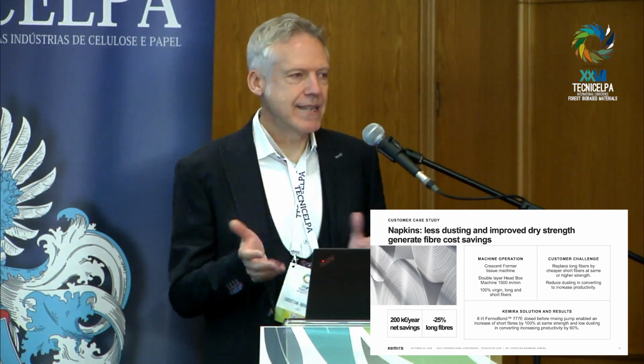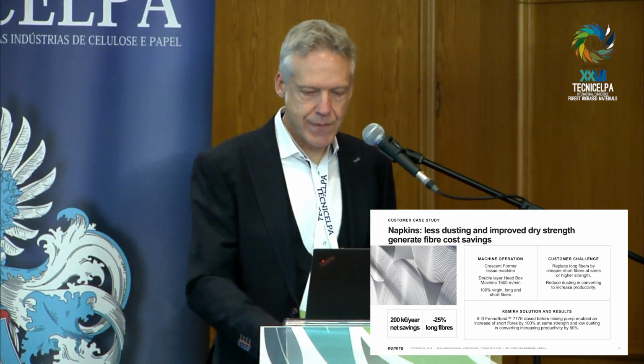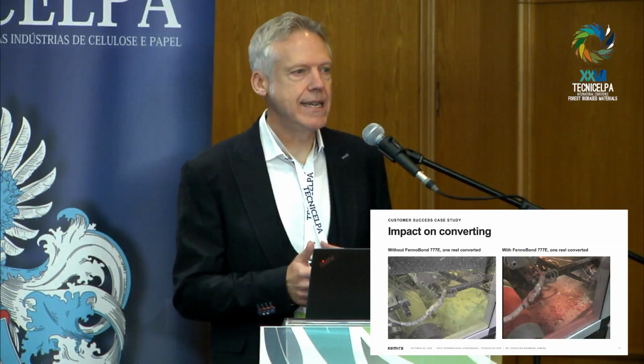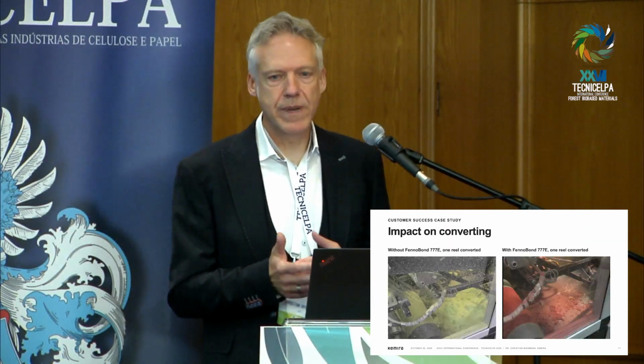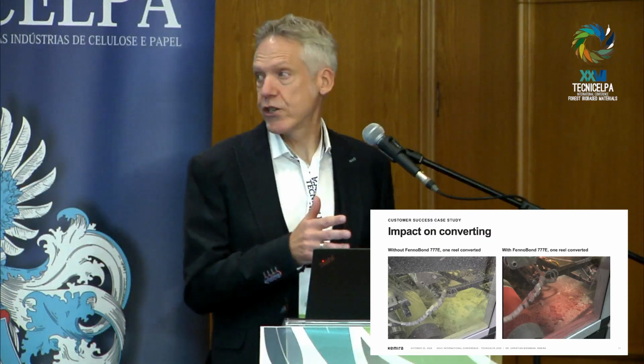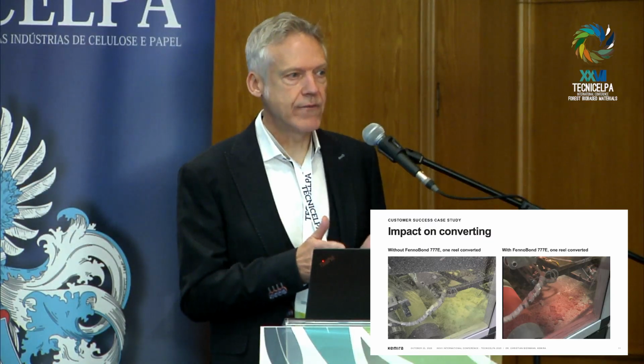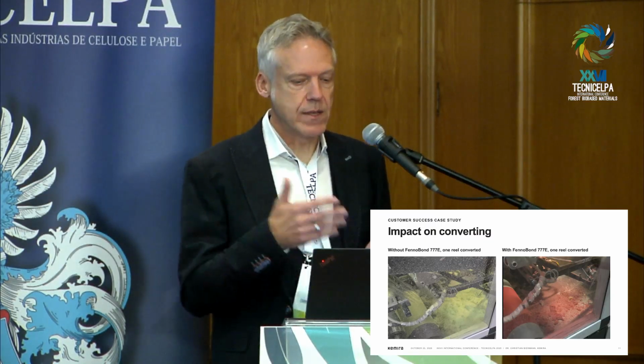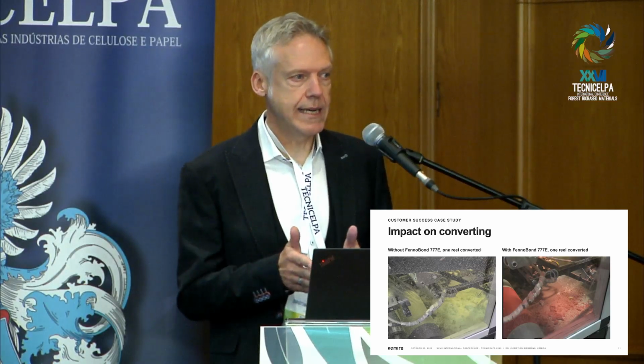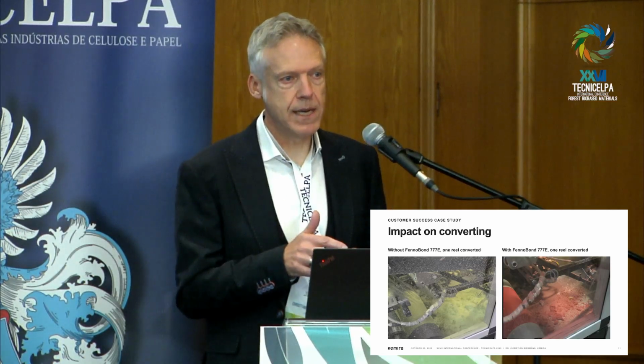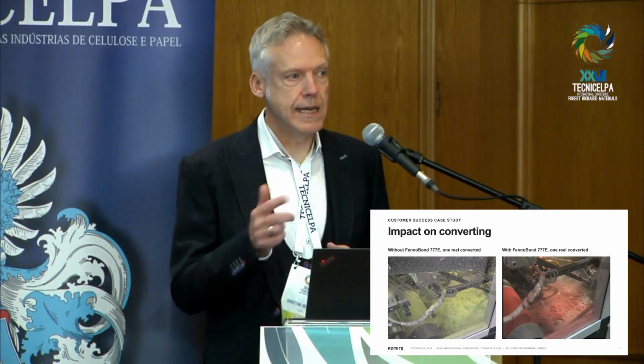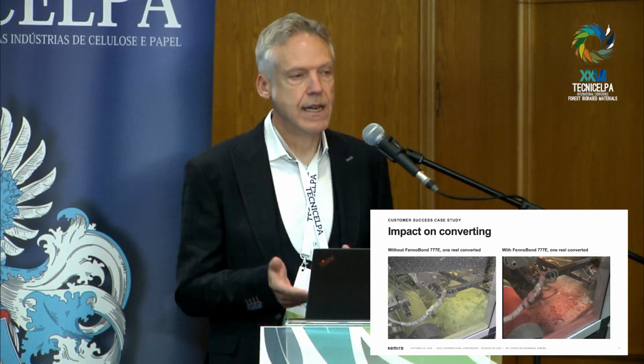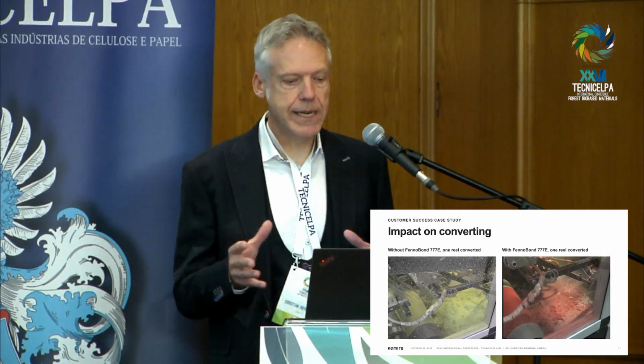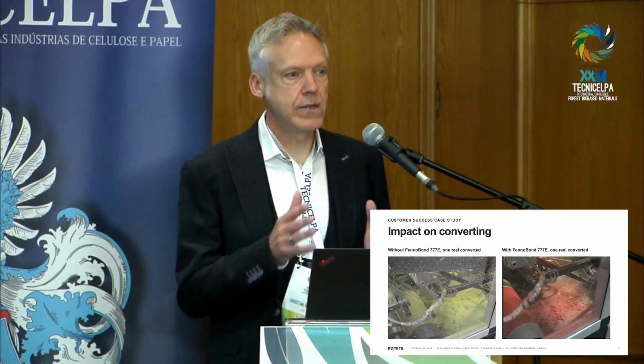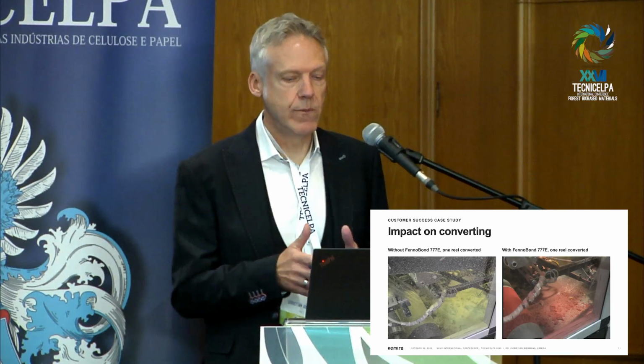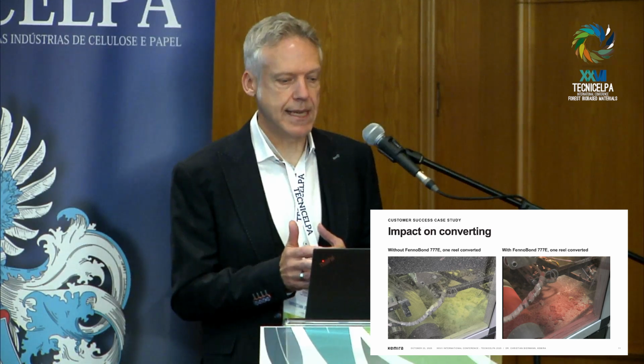when the customer started to convert the product, they saw that the cleanliness of the converting line completely changed. So on the left picture, you see the converting line after converting one reel. On the right picture, you see the converting line after reducing the long fibers, increasing the short fibers, and using the FENNOBOND 777E. So much less dust in the cabinet, and due to this, they need to clean after every 4 reels, which increased their productivity by 60%.